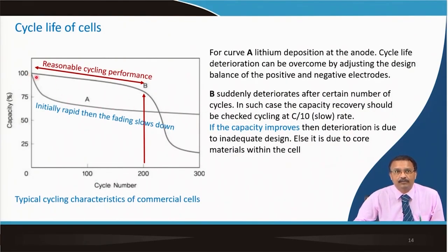One is, you see, it was reasonably good, and then suddenly at one particular cycle number, it drops down. This is better. Initially, it goes down because of the SEI formation, but after that, the rate is relatively less, and it is performing more or less okay. Although the capacity percentage is not okay, because after 300 cycles, no good cell will allow that capacity falls down as low as 50%. But had it been here around 85%, it would have been good.